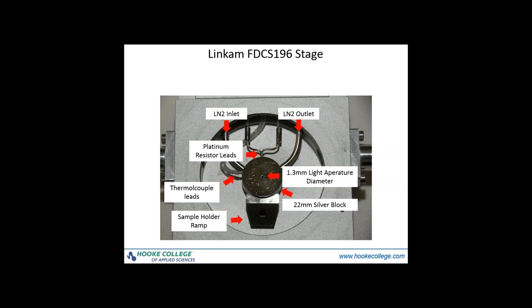Below that silver block, there is a coil, and then there's channels. And so therefore, as the flow of liquid nitrogen comes through and the electrical current goes in through the platinum resistor, it is accurately controlled for the rate that you want to heat or cool. So therefore, if you want to go down 10 degrees per minute, it will regulate that flow and that current on that platinum resistor to 10 degrees per minute or 5 degrees per minute. This system can go as slow as 0.05 degrees per minute or as fast as 150 degrees per minute in the heating and cooling. And the highest temperature that it will reach is 125 degrees and as low as negative 196.